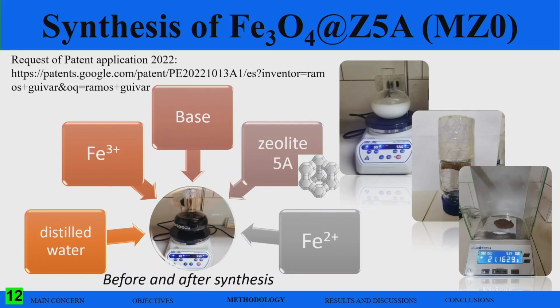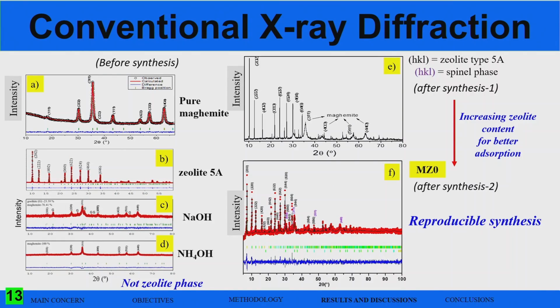All right, we do a before and after synthesis approach. We mix the nanoparticles with zeolite using it as a template in the before synthesis to see if it has some effect on the final product, and the after synthesis procedure to see if the zeolite mixture with the nanoparticles can also be a good adsorbent. So we apply conventional X-ray diffraction to the adsorbents. We have a control of pure maghemite here before synthesis, and some zeolite that is a very crystalline system. Actually, it's a mesoporous microcrystalline structure.